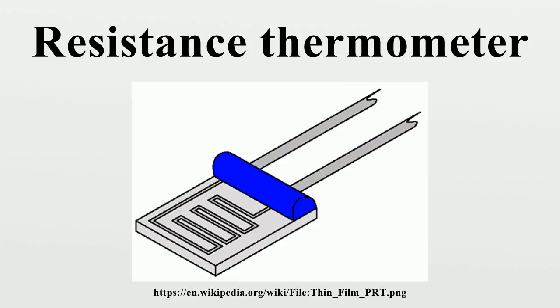Pure platinum has an alpha of 0.003925 ohm per ohm per degree C in the 0 to 100 degrees Celsius range and is used in the construction of laboratory-grade RTDs. Conversely, two widely recognized standards for industrial RTDs, IEC 60751 and ASTM E1137, specify an alpha of 0.00385 ohm per ohm per degree C. Before these standards were widely adopted, several different alpha values were used.